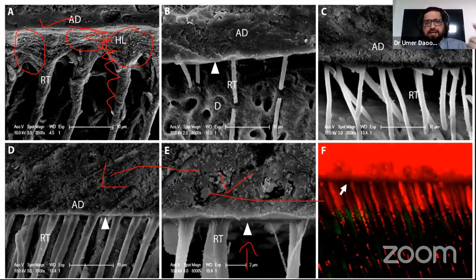So what was the idea? The idea was that the hybrid layer, like I said, is the weakest link, is creating a lot of problems. So with this strategy, we did two things. We took out the etching procedure completely while using the total etch. The total etch cannot be done without an etchant. So we took out the etchant completely, so that problem of activating the MMPs goes away. And we have taken out the hybrid layer from the equation completely.